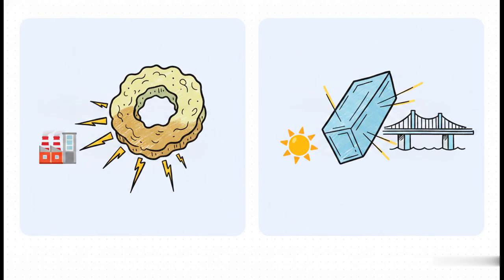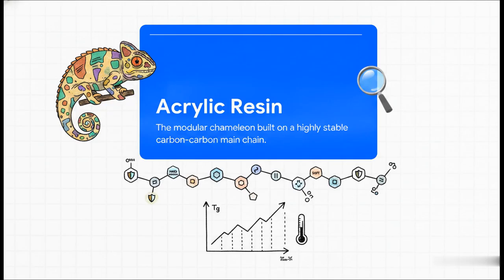The showdown between the 2 main types is really interesting. On one hand, you've got aromatic PU, made from TDI or MDI. It's highly reactive, great on the budget, but its chemical ring structure soaks up UV light like a sponge. It'll yellow super fast, making it an indoor-only player. On the other hand, we have aliphatic PU. Structurally, it literally cannot absorb UV light. It is chemically blind to the sun. Sure, it costs more, but it yields zero yellowing, making it the ultimate B2B sunscreen. If you're engineering a top coat over an epoxy primer for an outdoor bridge, aliphatic PU is your only serious answer. Moving on to resin number 3, acrylic resin.